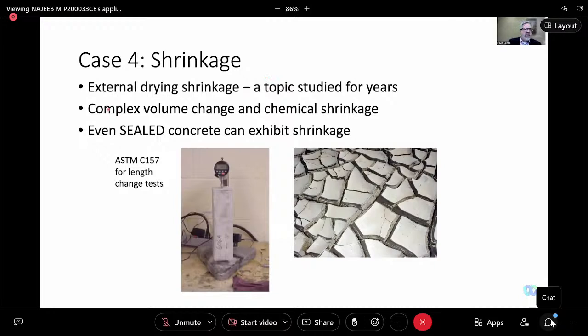So the early ages of concrete involve some complex volume changes and chemical shrinkage. And even sealed concrete can exhibit shrinkage. So you see here some basic testing of a sample using a standard C157 test. And then I showed this mud flat cracking as just an illustration of how we get curling when we have a gradient of shrinkage through the thickness.